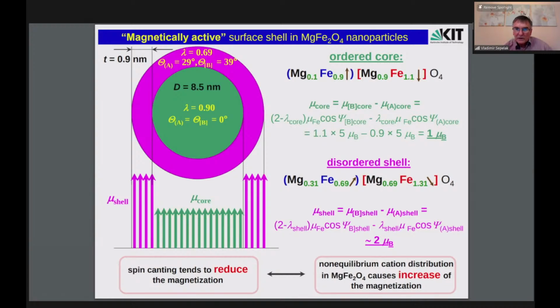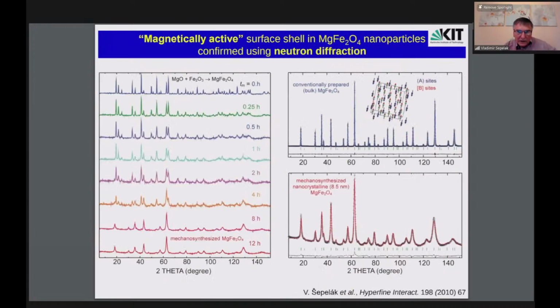This magnetically active surface shell in magnesium ferrite nanoparticles was also confirmed using neutron diffraction. I will not go into details.